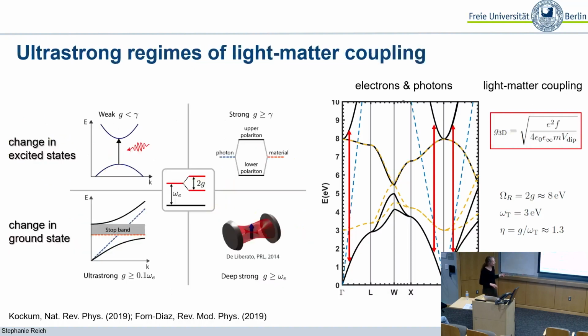These were the regimes we discussed before: the weak coupling regime and the strong coupling regime, where you had a change in the excited states of the material. And now we moved into the so-called regime of ultra-strong and deep-strong light-matter coupling, where the interaction strength is comparable or even larger than the bare excitation frequency. What happens then is that you still have a change in the excited states, but at some point you should also expect the ground state of your system to change, because you can no longer deal with a separated Hamiltonian.